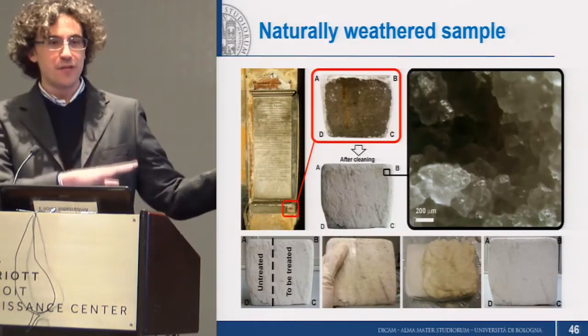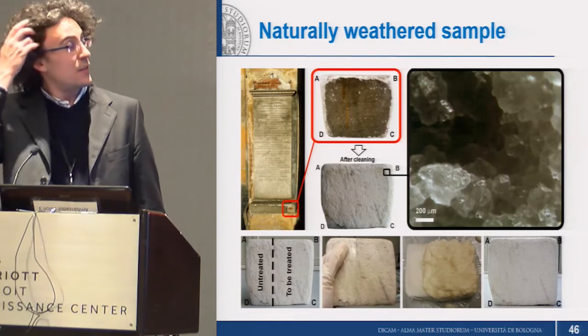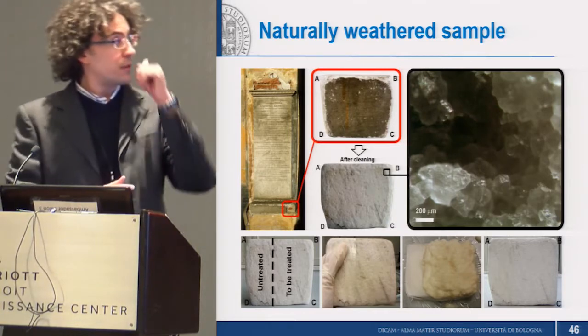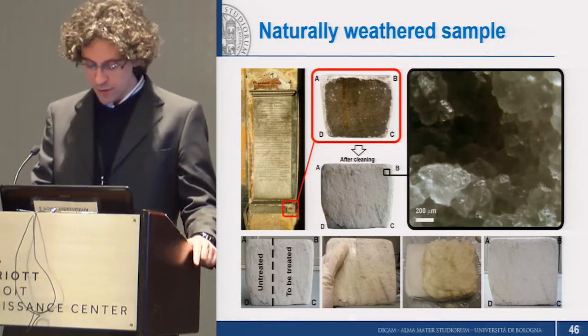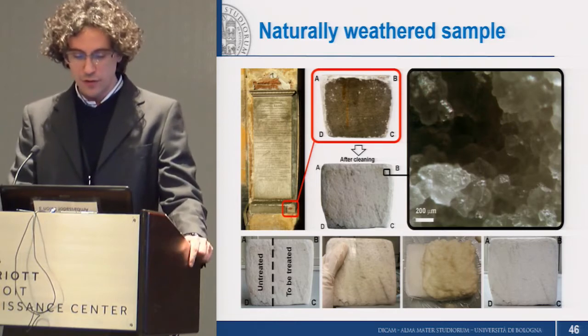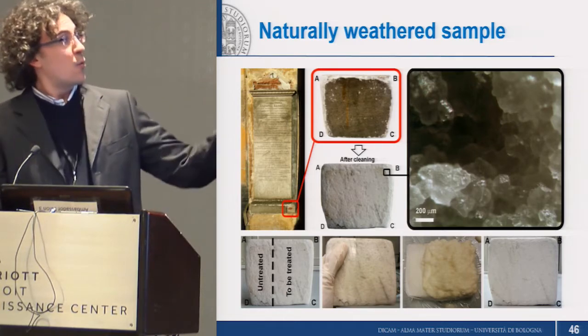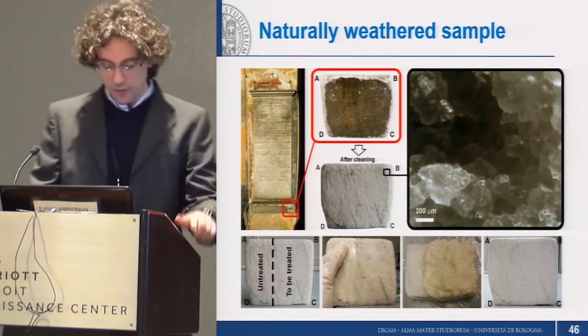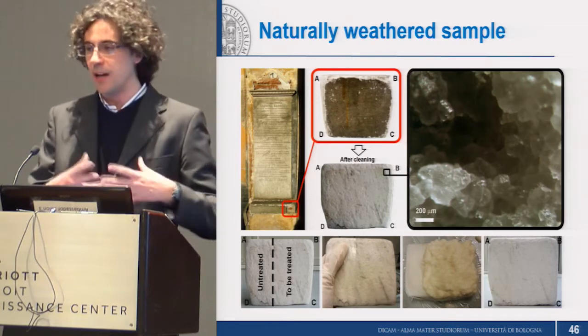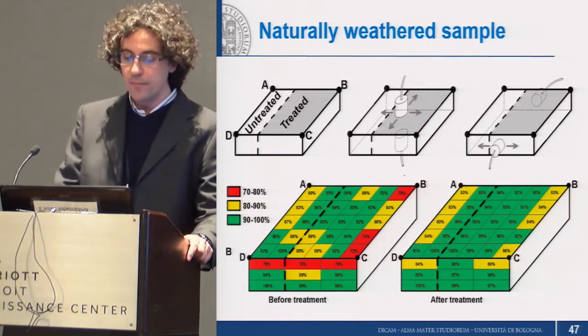So, after doing all these preliminary tests on the artificially weathered marbles, we moved on to some naturally weathered marble, as you can see in this picture. So we carried out the treatment. We found that, again, by ultrasound, which is not destructive, the mechanical improvement was satisfactory.